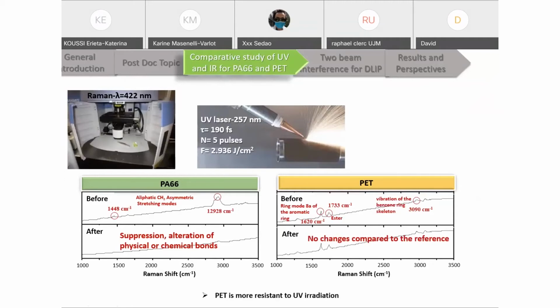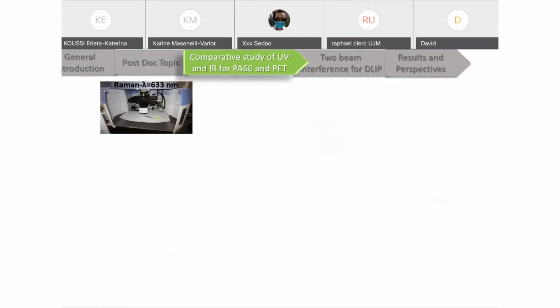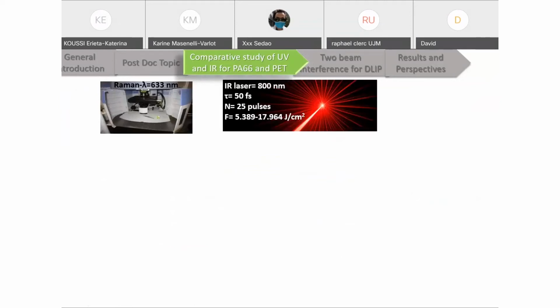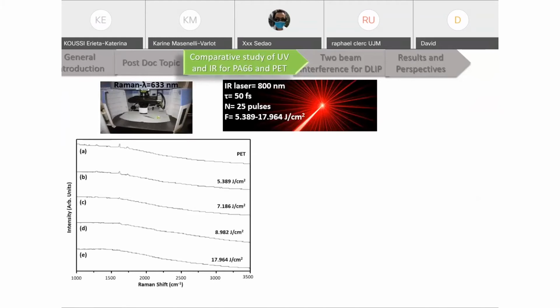So we do the same thing for the IR irradiated sample. We have selected those samples that were irradiated with 25 pulses in order to avoid the deep holes. To this analysis, now we have varied the laser fluences. So the 2 characteristic peaks before irradiation are at these regions, and due to the laser fluence increase, these peaks appear to be suppressed.